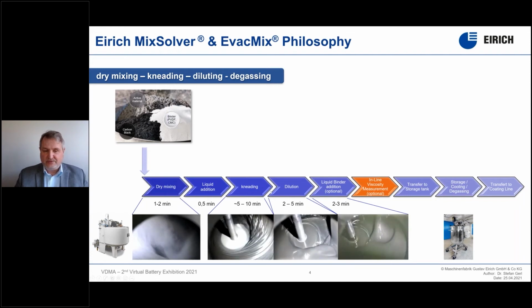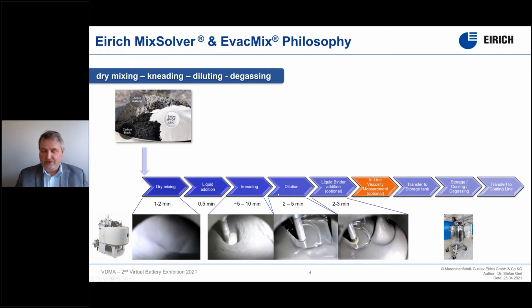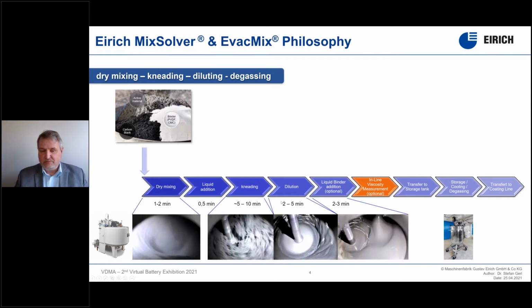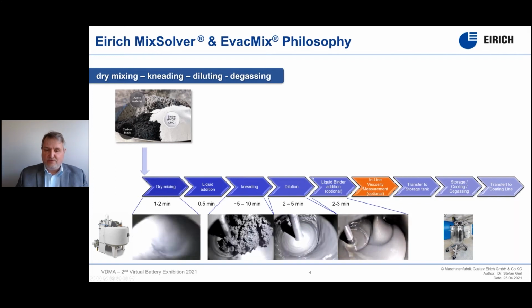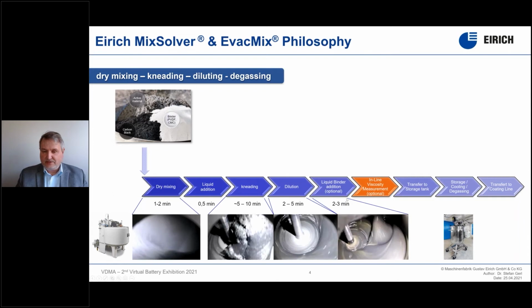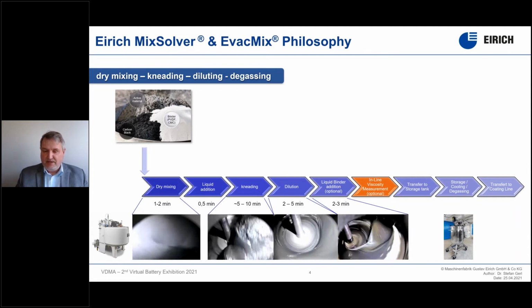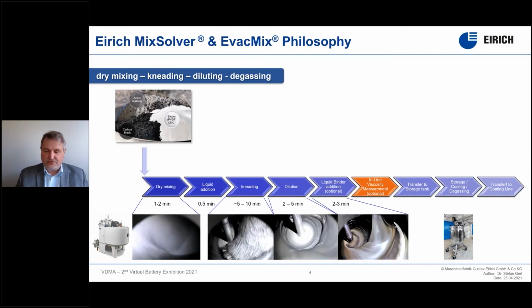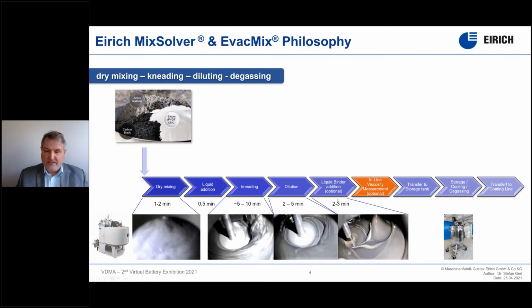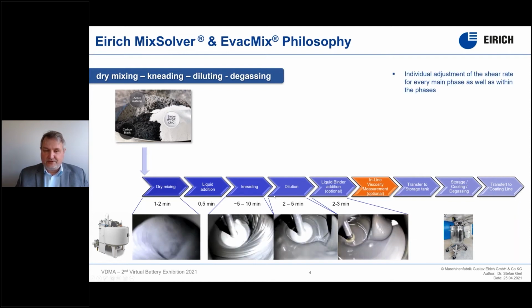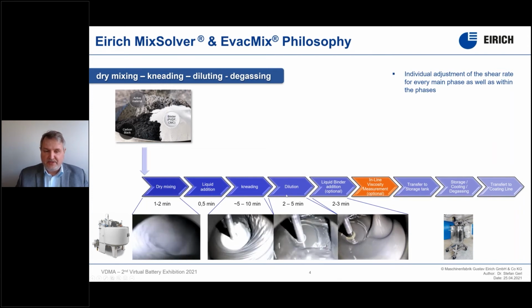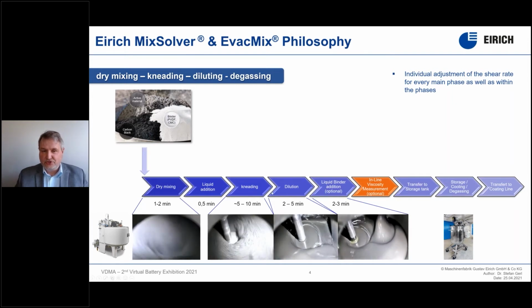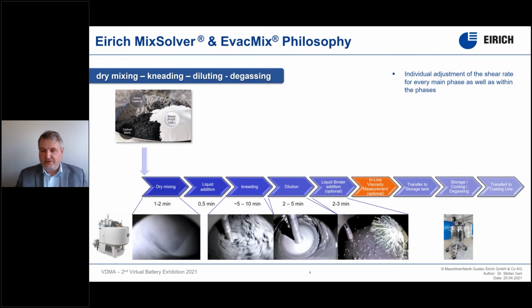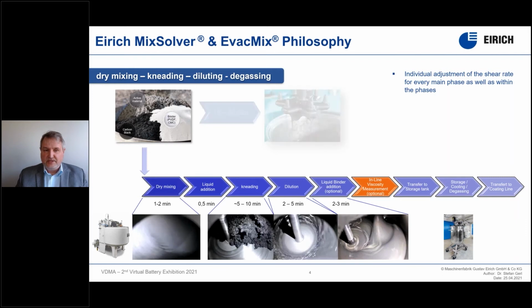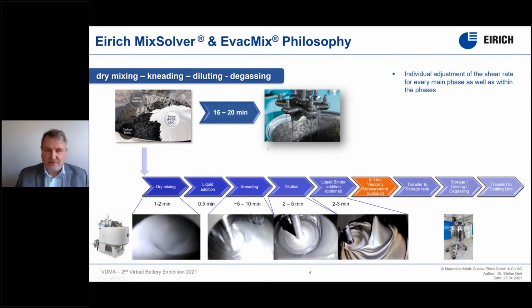After this very important phase, we have to add the missing liquid. We call it a dilution phase. This can be made relatively quickly, within 2 to 5 minutes. And for water-based anode systems, we add then in the final end the liquid binder like SBR, which is done at very low speeds, not to stress the sensitive binder too much. The shear rate, the speed, the time can be individually adapted in every phase, and even phases can be split into sub-phases to allow excellent shear stress, to allow excellent dispersion of the raw materials. The total preparation time takes between 15 and 20 minutes.